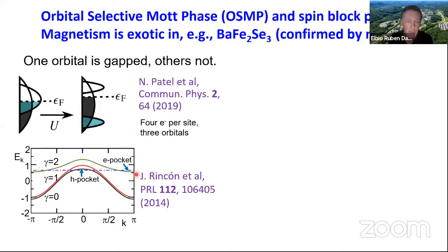For example, for the type of models that we have used, for the case of three orbitals, we have an orbital that is barely populated with electrons, so it has electron pockets here and here. And then there are two near degenerate orbitals, which are almost entirely populated. So there is a hole pocket at the center. So this is our attempt to capture a little bit of the physics of the iron superconductors. We have a pocket at the center and two electron pockets at the extremes. And the real material has also two electron pockets along the other axis.